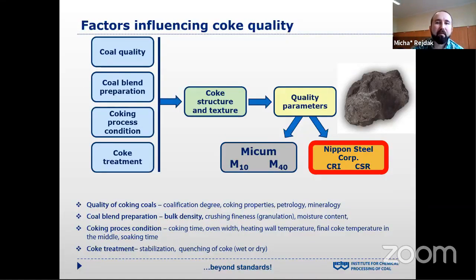Here we have factors influencing coke quality. As I mentioned before, the main determinant of coke quality is the quality of coking coals. I mean qualification degree, coking properties, petrology, mineralogy. The second factor is coal blend preparation. I think the most important in coal blend preparation is bulk density, because in general, the higher the bulk density, the better the coke quality. But also the other factors are important, like granulation of coal and of course moisture content, because both crushing fineness and moisture content also influence bulk density, so it directly affects the coke quality.